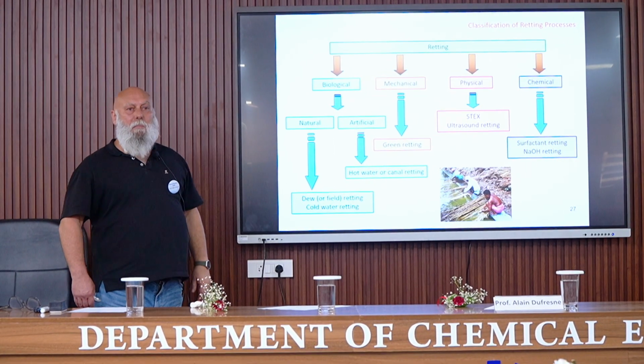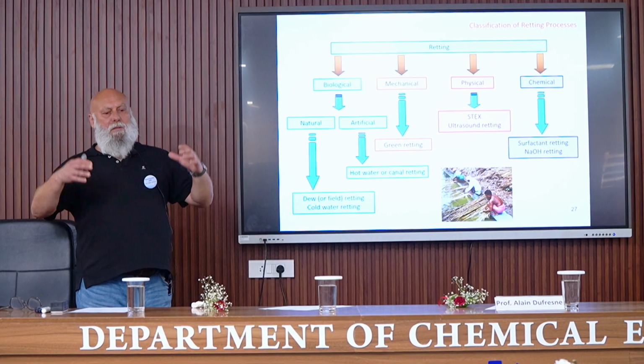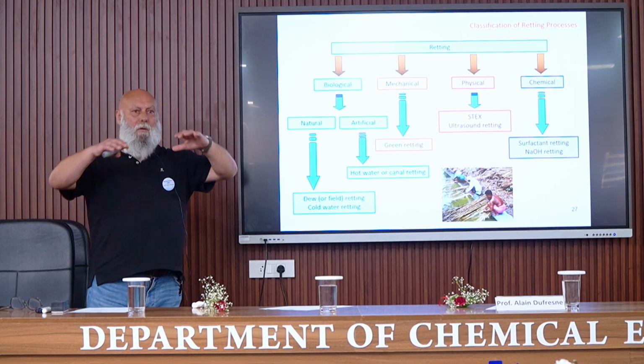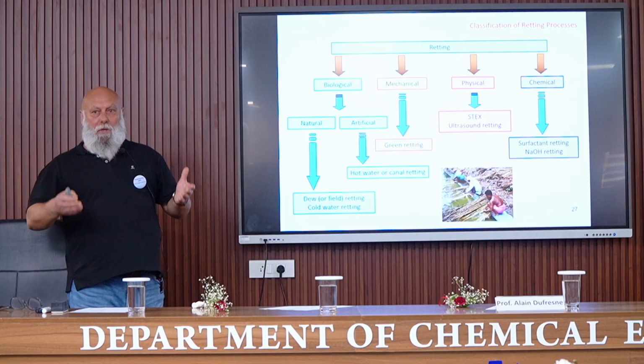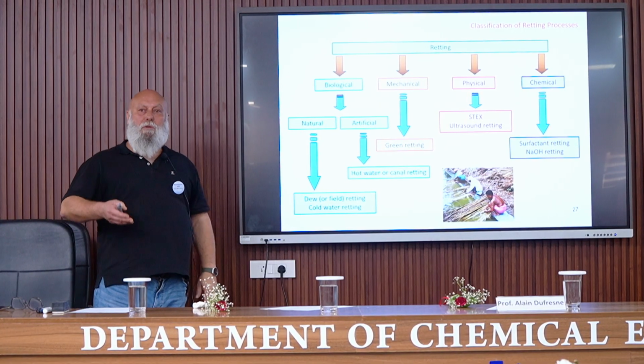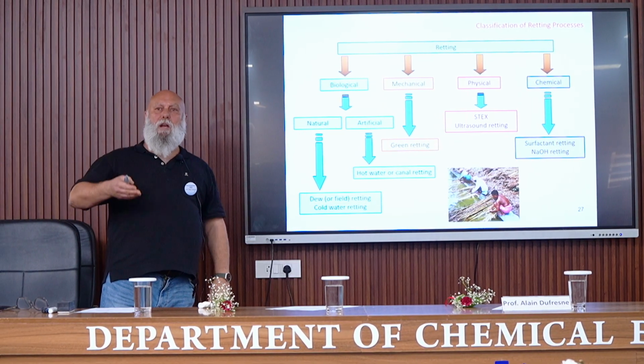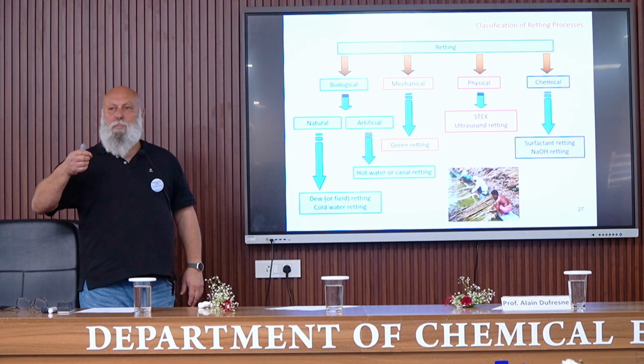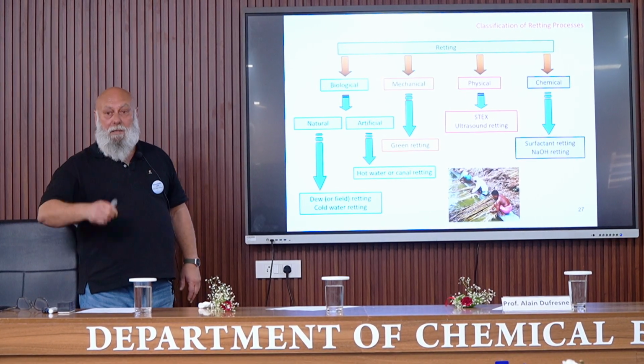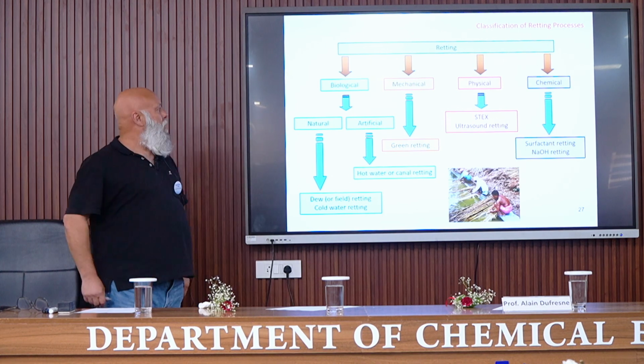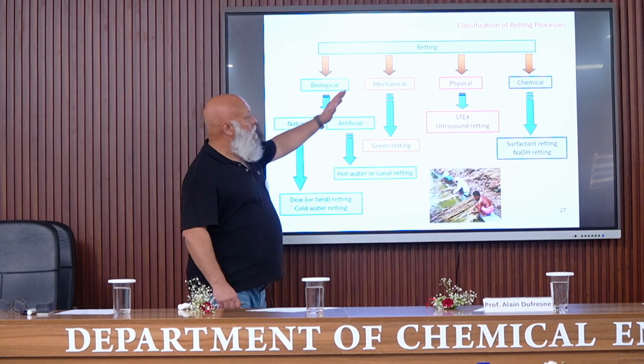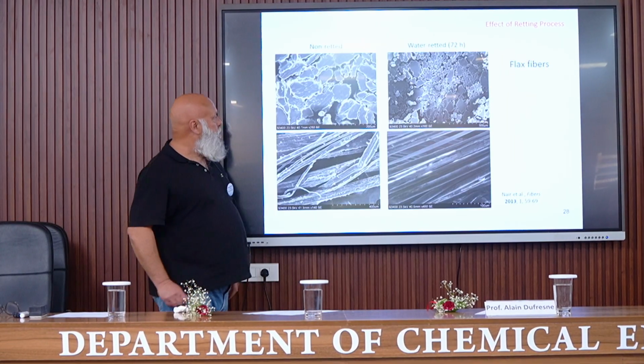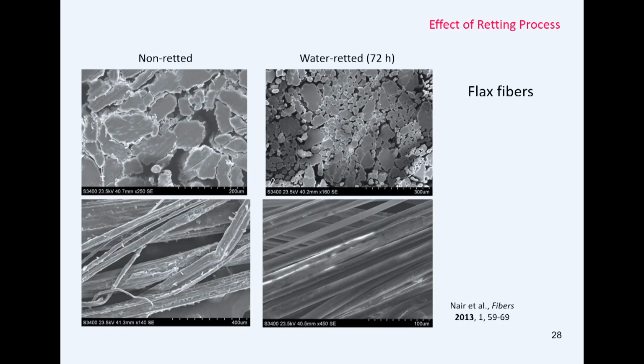So steam explosion consists in inserting the natural fiber in a container containing water in which the pressure is increased and the temperature is increased. And the pressure is suddenly released in order to explode the natural fibers. Or it can be a chemical retting process. You can see here the impact of this retting process on the aspect of the natural fibers.